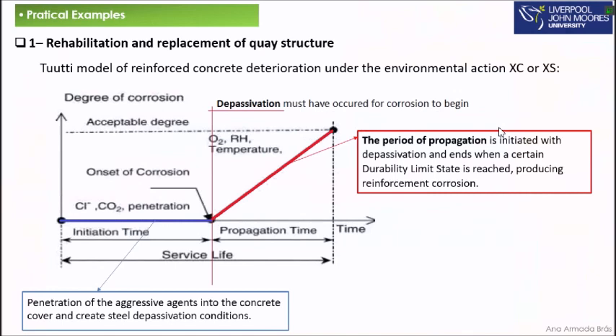So we use the Tuutti model of reinforced concrete deterioration under the environmental action of carbonation, which is Xc, and chlorides, Xs. And the model includes the prediction of the initiation time. So you have here the initiation time and the propagation time associated with the process. The initiation is the first period, mainly dependent on chlorides and CO2 penetration, and it's the penetration of the aggressive agents into the concrete cover that creates the steel depassivation condition.